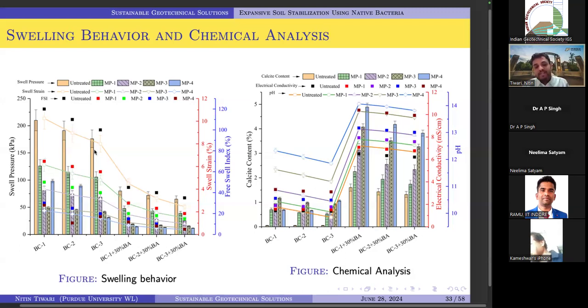But at the same time, when you added the bottom ash, it already reduced to 100 kPa. And with the treatment, it goes really down to around 5 kPa. So from the soil having 220 kPa of upward swelling pressure, you're reducing it a lot, to just 10, 15 or minimal swelling pressure, to be honest. The same goes for strain and for free swell index. So all three parameters worked out perfectly. Let's move on. Now we went to the calcite content, to see whether calcite is really forming or not.